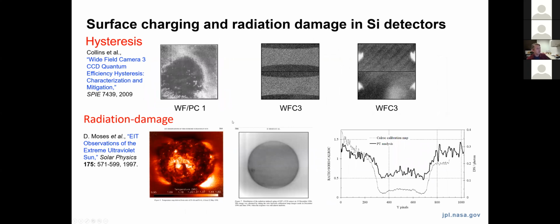So I'll talk about how we fix the dead layer problem, but I'll first mention that if you don't address this problem in a fundamental way, it can lead to other issues in operating back illuminated silicon devices. These are all CCD sensors here from various space instruments showing effects like quantum efficiency hysteresis and radiation-induced damage that essentially is related to variations in interface state trap density as a function of either radiation, time or temperature that cause, in some cases, permanent changes to the efficiency of your device. And so it's not only a matter of improving the quantum efficiency, which I'll talk about, it's also a matter of improving the stability of back illuminated devices.